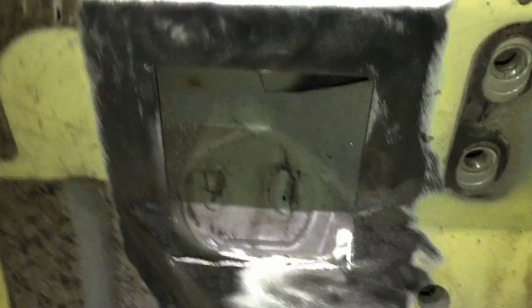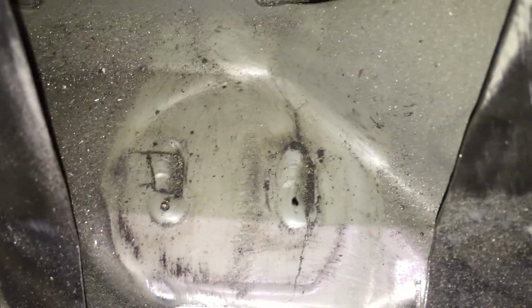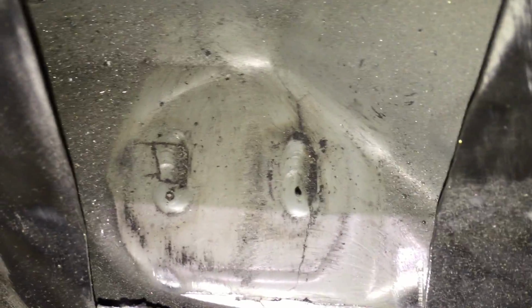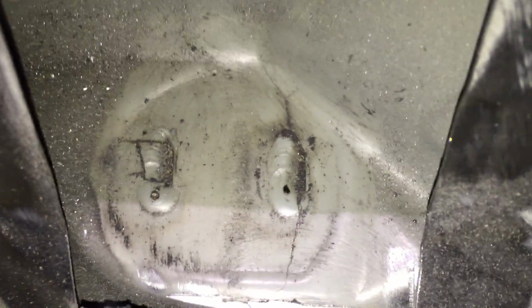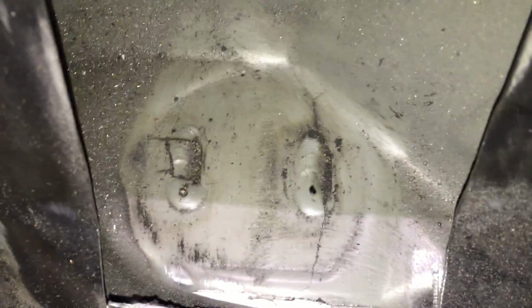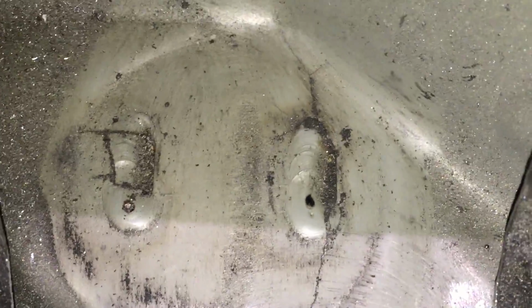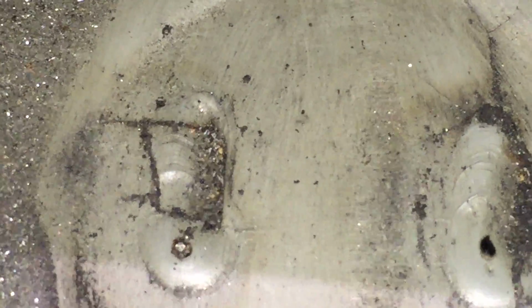We've now cut access holes in the rear seat panel to expose the front top two MIG welds holding the rear subframe front pair of mounts. These are the only thing that hold the threaded receiver to a sheet metal panel, and sometimes the MIG welds crack or get splits through the middle of them, like that one on the left. Several cracks going right through the middle of that MIG weld, and then sometimes the cracks are just down the side of the MIG weld through the sheet metal work down here and then going up that way, branching off a little shoot off to the right, one off to 11 o'clock.